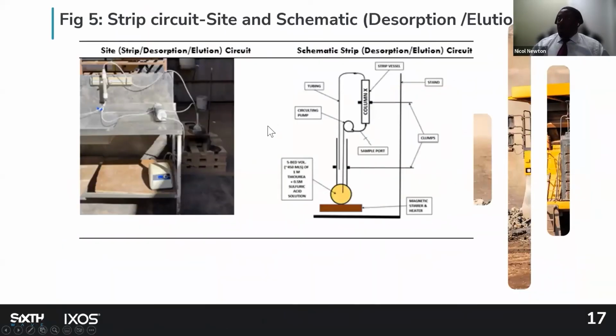With the strip, one of the good things that we realized, well, this was a setup we put together for the strip, both the sites and then the schematic design. It was more like a continuous strip circuit. This was done under ambient pressure and ambient temperature. There was virtually no pressure buildup in here. And it worked perfectly as compared to what we are known to use for carbon when we use the AARL circuit or the Zadra circuit.